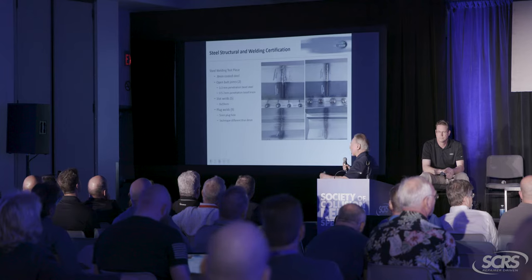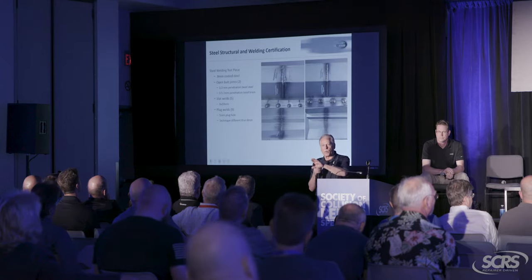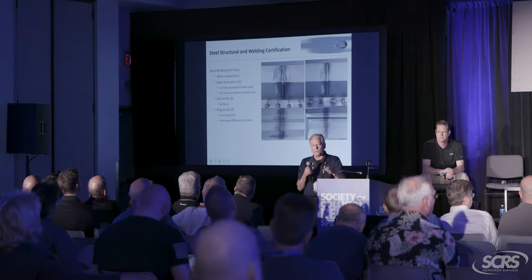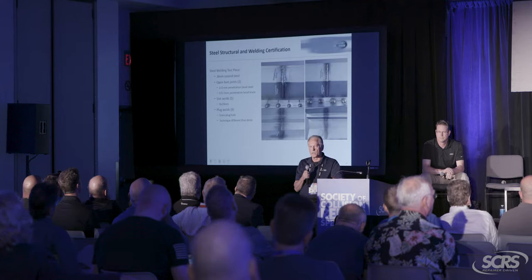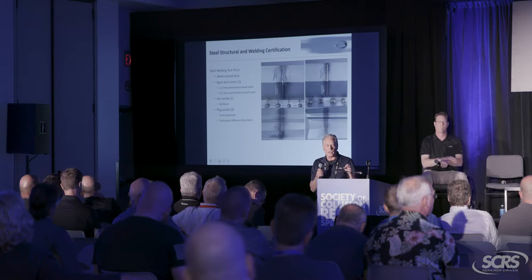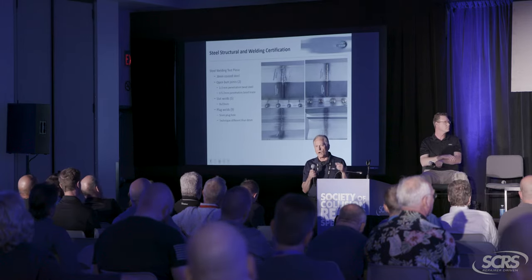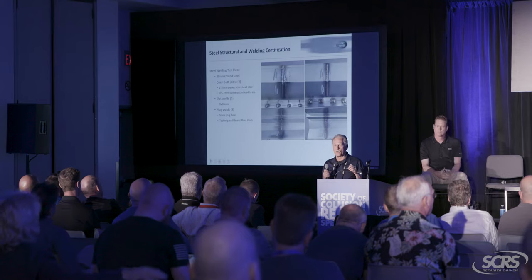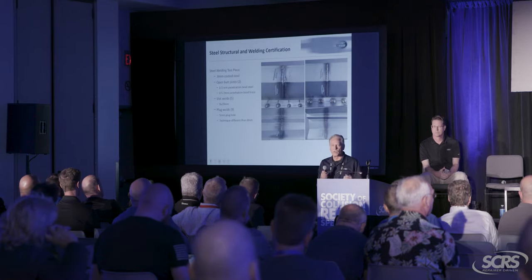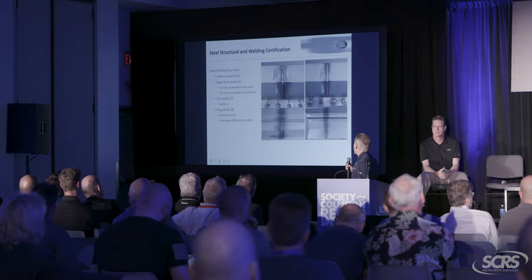So when you're looking at the left upper, it looks really nice on the outside, but we cut that part open, and on the inside, there can't be any flaws. We have a much higher fail rate on the steel weld than we do on the silicon bronze, just because people are not used to getting that type of penetration. And when you are welding like that, it's really easy to burn a hole and burn it up. So it takes a little bit of a knack to get that.